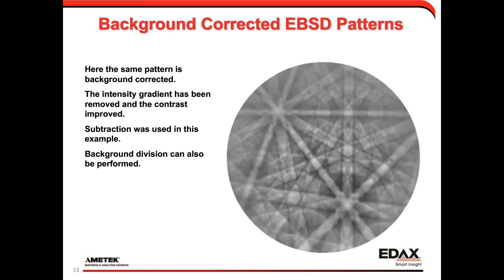Generally what we do is some sort of background correction. We take an average intensity gradient from multiple different grains with different orientations to blend out the spatial information. We save that as a background, and then we either subtract it or divide it from the live image, and we get a pattern that looks like this. This is what we call a background corrected EBSD pattern. That intensity gradient has been normalized away, and the contrast is improved, and this type of pattern is generally pretty easy to analyze with the band detection algorithms and determine the correct orientation.